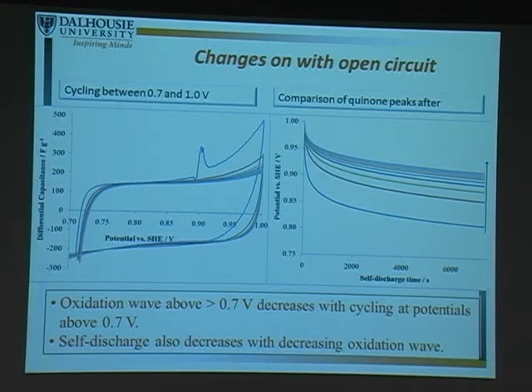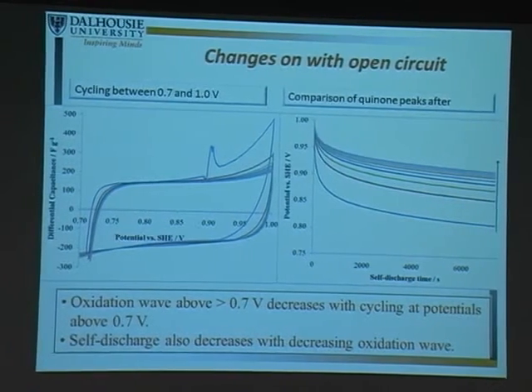Oxygen can be reduced to hydrogen peroxide. Hydrogen peroxide might actually react with our carbon surface. So could we be forming these quinones by having the peroxide doing some chemical reactions on the surface? So we decided to stay above 0.7 volts, that way we're not doing any oxygen reduction, and we see exactly the same thing we saw before. So we're not actually forming peroxide, or if we're forming peroxide, it's not the thing that's causing these changes.